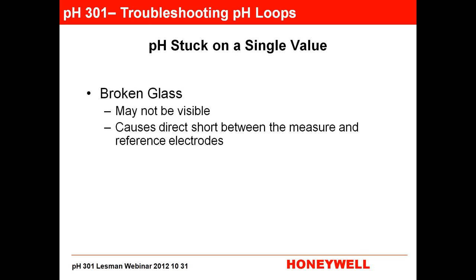Okay. Sometimes you get your pH stuck on a single value. That is almost always broken glass. That means that there is a direct short between the measuring electrode and the reference electrode. You can imagine that if the glass is broken, if the bulb is snapped off, that's very obvious. You pull it out and you go, oh, well, it's no good, throw it away, put in a new one. But sometimes you can get hairline cracks that you can't see in your measuring electrode unless you put it under a microscope. And that hairline crack is just enough to let fluid enter there, and then you just get that dead short. The other place you can get it is inside the body of the sensor.